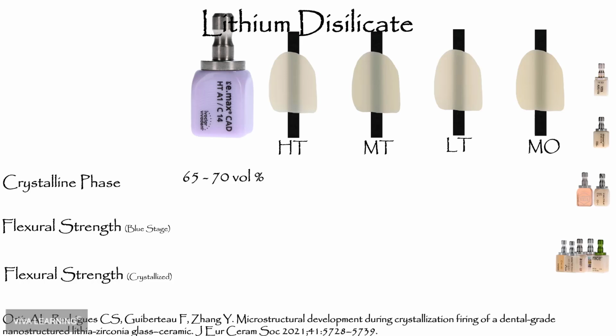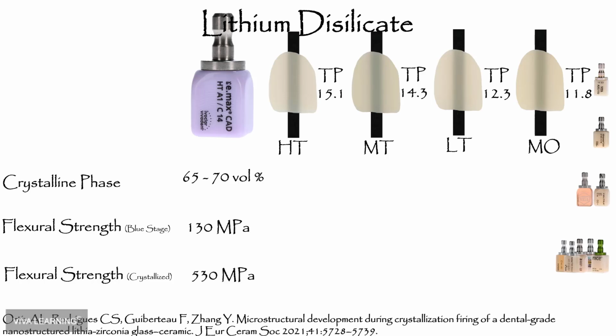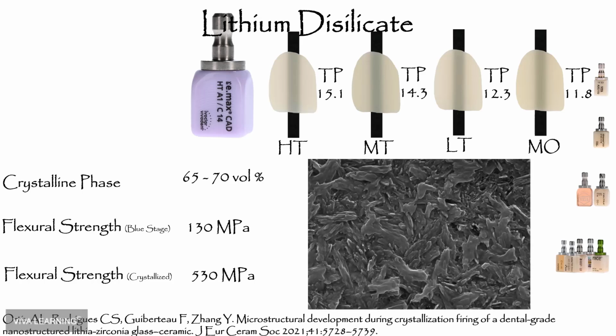They maximize the amount of crystalline phase to 65 to 70%, and they come with different translucencies from the lowest translucency to highest translucency. They can offer us a range of translucency, and they're easier to mill. For example, IPS e.max CAD is easier to mill in the blue stage, and when it's fully crystallized, it gains the highest strength. And they do have long rods of crystals embedded into each other, which creates a good scaffold so that it prevents fractures propagating into the material.